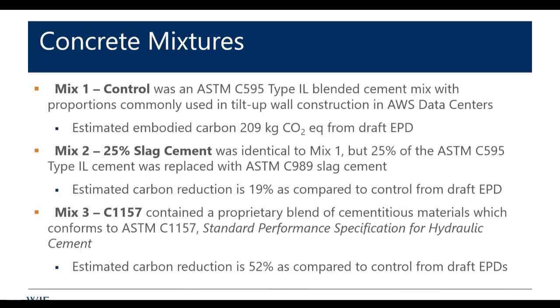These are the mixes in summary, and I have a table coming up that'll flash by that has a lot more information than this. But the bottom line is the number 1 mix, standard mix, type 1L cement. It was coming in at about 209 kilograms CO2 equivalent per cubic yard. That's because it was using St. Genevieve 1L cement, and we were just down the street from the St. Gen plant. So we had a very low carbon cement with close proximity. Next mix had a 25% slag. That reduced our greenhouse gas numbers by about 19%. And the third mix had very little, if no clinker, 100% alkali activated material. They won't tell us what it is, but I think you can probably make some assumptions. But that one gave us about a 52% reduction. So we're just about 100 kilograms CO2 equivalent per cubic yard.